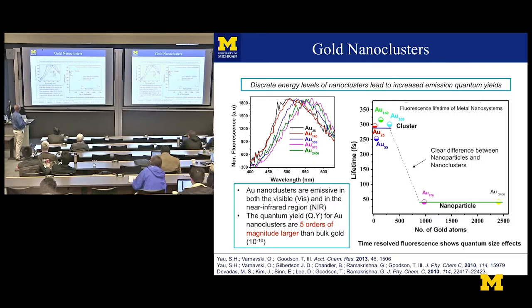So here's the normalized fluorescence, and this is for these gold. Let's get some fluorescence in the visible. But you can read this statement. So gold nanoclusters are emissive in both the visible and the near infrared. And we found the quantum yields for gold nanoclusters are 5 orders of magnitude larger than what you would obtain for bulk gold. 5 orders of magnitude.